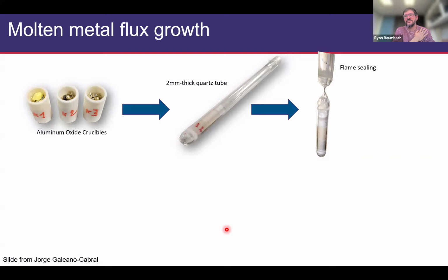There are many materials that you can grow in the absence of quartz. I think it's just an interesting side note. And the other thing that I want to tell you about is that if you work in a lab that has been around for a long time, it may have both quartz and Pyrex in it. Probably someone in the demos will show you this, but you can always tell the difference between Pyrex and quartz by looking down the axis of the tube. The Pyrex is going to look green and the quartz is going to look white. So always be on the lookout. Don't get those two things mixed up.